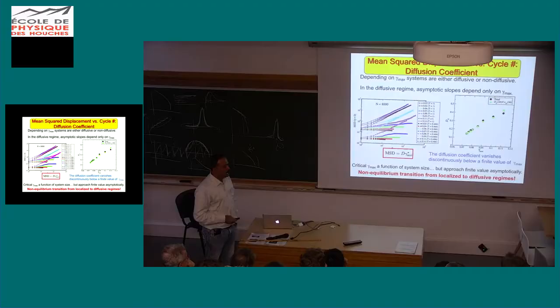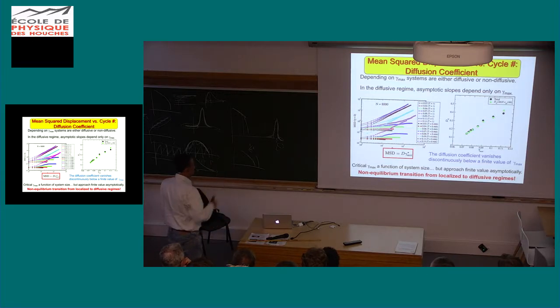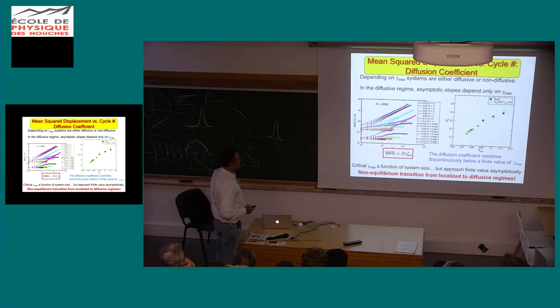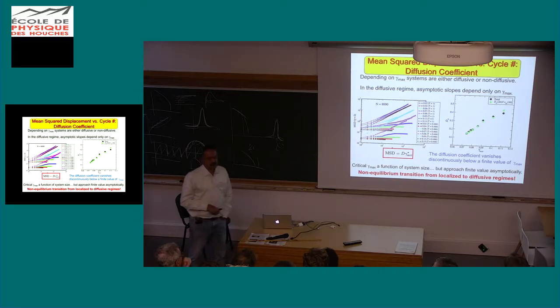We also look at how particles move as a function of the number of cycles, and treating the number of cycles as a time variable, we can define a mean squared displacement, and from that a diffusion coefficient. These mean squared displacements, again, above a certain threshold amplitude of about 8% here, reach a common final state regardless of initial conditions, and more importantly, the mean squared displacement is linear in the number of cycles. Again, I emphasize we're looking at configurations one at the end of each cycle. On the other hand, at smaller amplitudes, the mean squared displacement saturates and the system becomes localized.